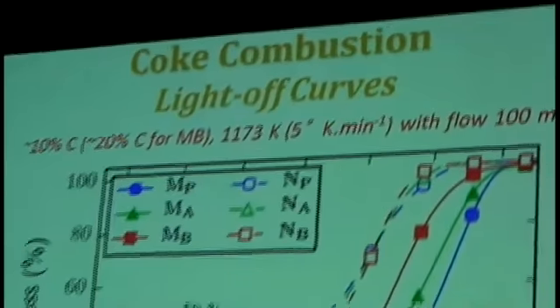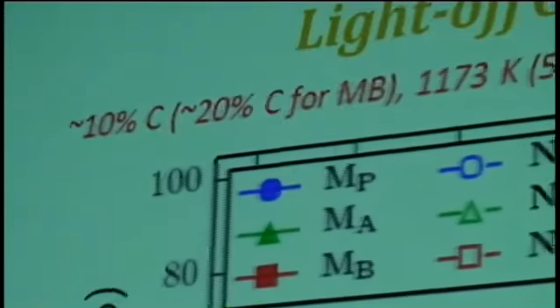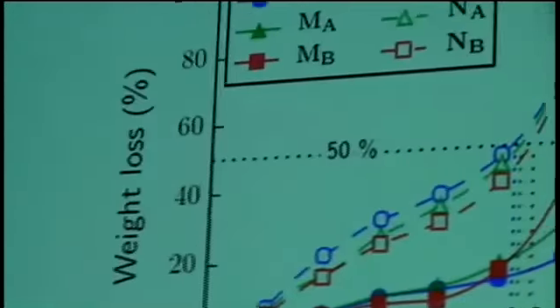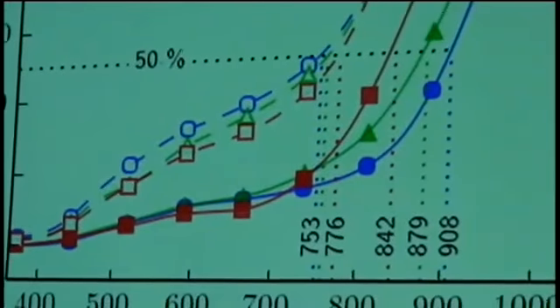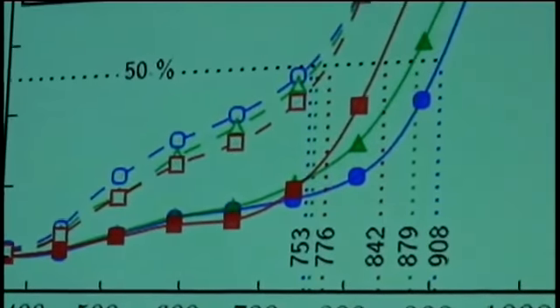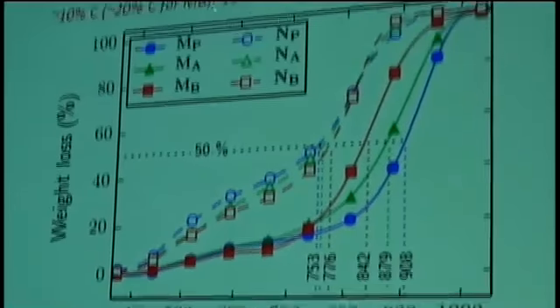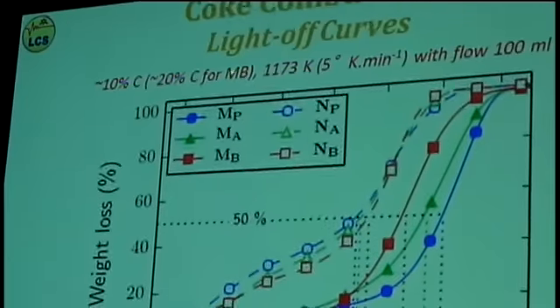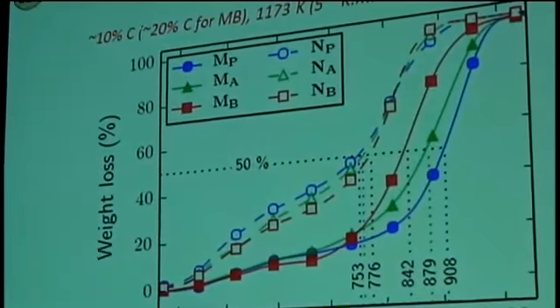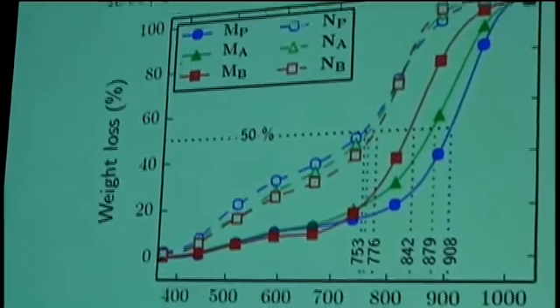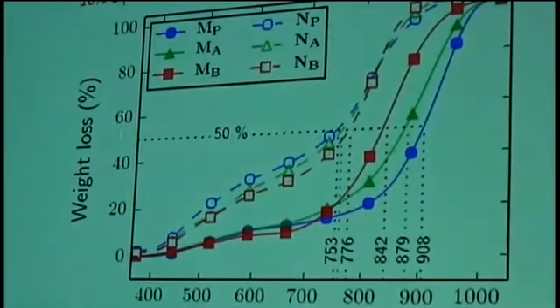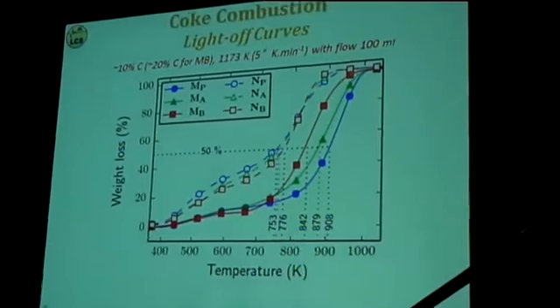Now, once you have put coke on a zeolite, you want to remove it, so you do some decoking. You just remove the catalyst from the unit. Here we took the catalyst that contained, of course, 10% of coke for all the samples, with the exception of the micron-sized crystal treated with a caustic solution, where there is 20% of coke. So this is a relative weight loss, and for this material the absolute scale is bigger.